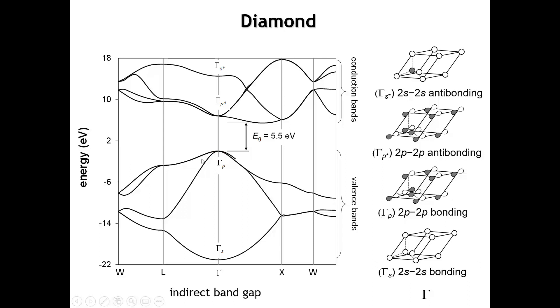One distinction here: when we say that we have antibonding interactions within the bonding MO band, what are we talking about? Let's look at this picture. Notice that we can choose the interaction so that the two-atom motif of the unit cell is bonding. But that does not make the interactions of this two-atom basis set with the two-atom basis set in neighboring unit cells bonding. So we may have one bonding interaction, but we also have antibonding interactions to carbons in neighboring unit cells. So this state, we're calling it gamma P. That's not to say it's all bonding or antibonding, but a bit of a mixture of both. Then we get four more bands, and the difference here is those come from an antibonding combination of the two-atom basis set here. So there's an antibonding S band, and then we have three antibonding P bands.